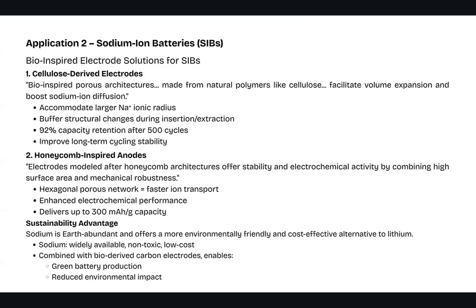Honeycomb-inspired anodes. Electrodes modeled after honeycomb architecture offer stability and electrochemical activity by combining high surface area and mechanical robustness. The hexagonal porous network gives faster ion transport and enhanced electrochemical performance, and delivers up to 300 mAh per g capacity.